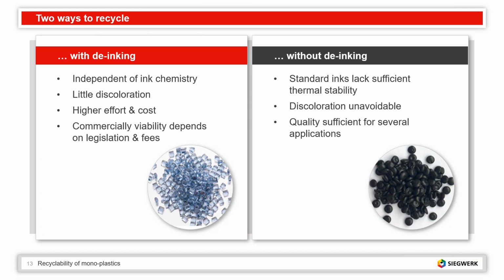If we look at the right-hand side, if we go without de-inking, which is possible and needs less investment, the challenge is that the standard inks of today lack thermal resistance and stability, and I will come back to this in a second. Because the pigments, the printed design, are still on the plastic film in the re-extrusion process, the discoloration is unavoidable and will be much stronger.